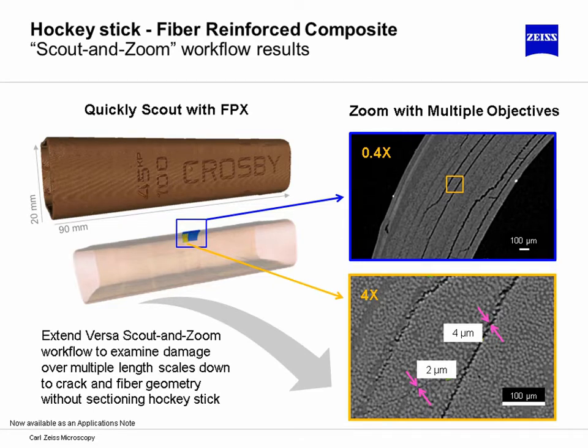That's also depicted on the following slide in a carbon fiber composite. This is a chunk of a hockey stick, which was undergoing some load and 3-point bending, and the failure at some of these joints was investigated. This is about 90 millimeters in length, 20 millimeters in height, and the flat panel extension can easily and quickly image the large specimen, but then even zooming in with the 0.4x and 4x lens, completely non-destructively without sectioning the sample, you're able to obtain resolutions down to being able to detect individual fibers within the sample, and obviously the cracks that are contained in here as well.